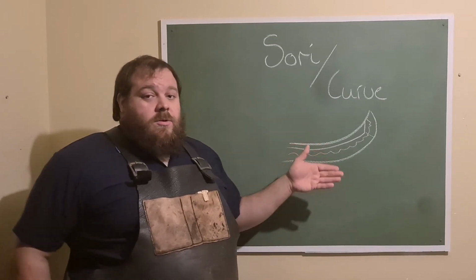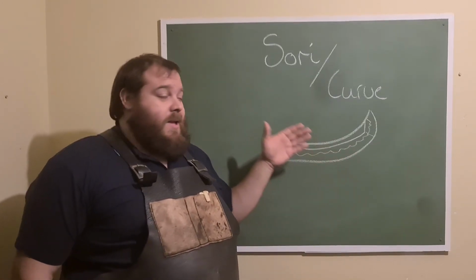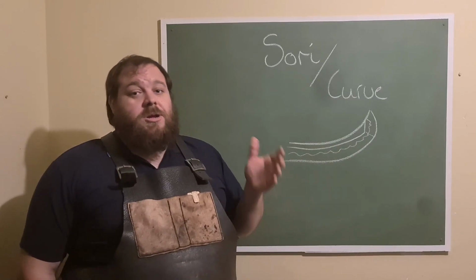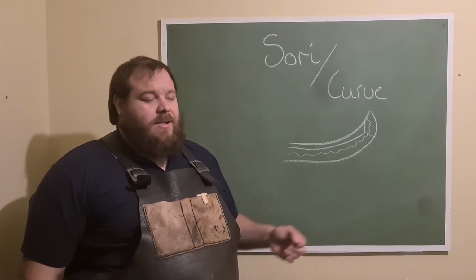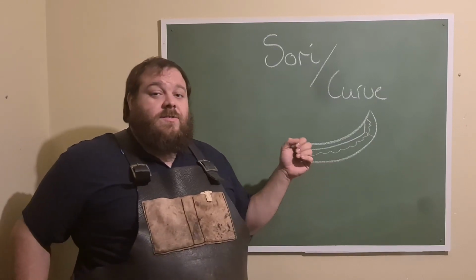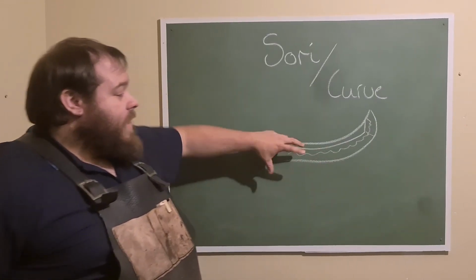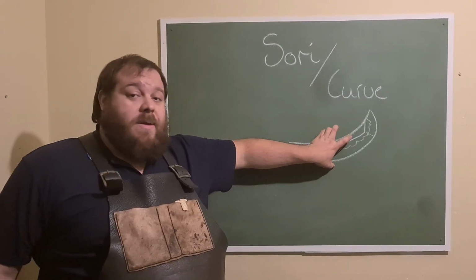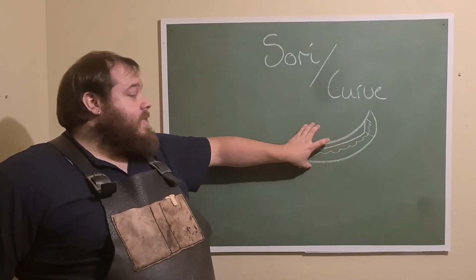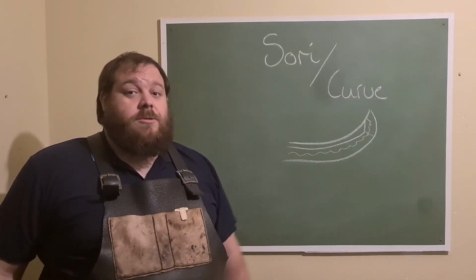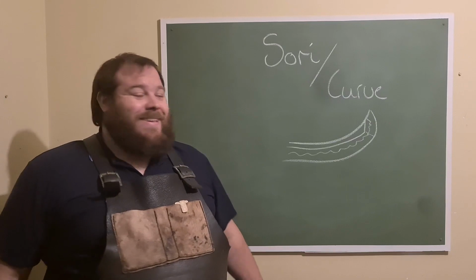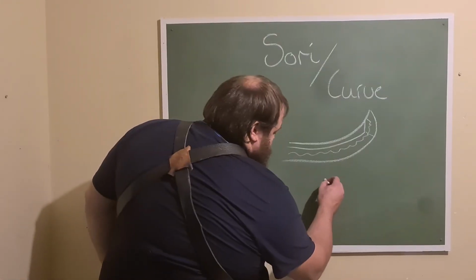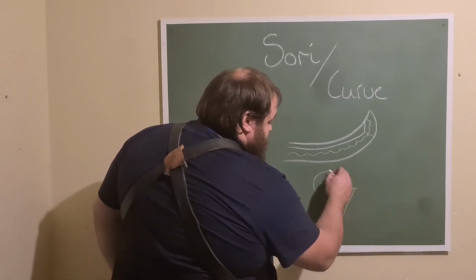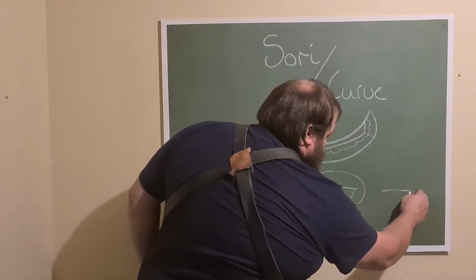Now, there are a couple of things you can do to fix this or to avoid it. One is to pre-curve, which is almost impossible to judge well unless you've practiced it and you know exactly what you're doing. The other is to just accept it. If your blade is short and wide enough, then there will be no sori. But in the event you don't want it, there is a really easy solution. Don't clay your spine. And when I say that, if I am talking about the cross-section of a knife blade, let's just say this is your knife blade, instead of applying the clay like this, we instead apply like this.